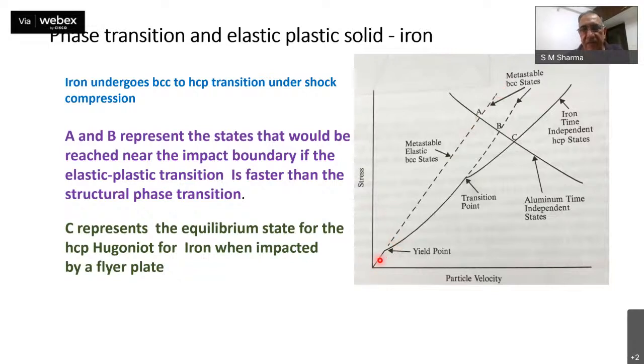And so elastically, if it stayed elastic, this is how the dotted curve would be loading the shock wave. And actually, beyond a yield point, or the Hugoniot elastic limit as it is called, it will take this curve. But before it completes this, it has undergone a phase transformation. So there's a transition point, and instead of this dotted curve, it takes this curve. So this is also a metastable state, because plastic deformation precedes the transition, but the phase transition does not let it persist forever. And the moment there is a phase transition, it evolves into this PU curve. And so this is the stable, equilibrium PU curve of iron.